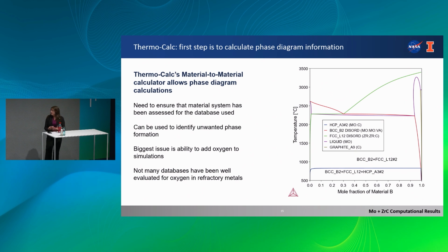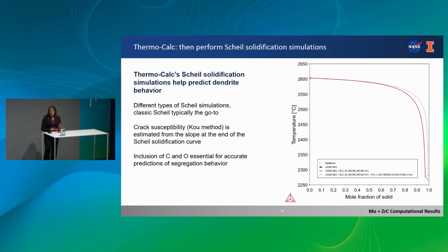So we did a little bit of phase diagram modeling first to determine whether or not we might get some unwanted phases forming. And the biggest issue, though, with this is that a lot of databases, for refractory metals, do not actually include oxygen. And oxygen and carbon can really have a big impact on your properties and the phases you see formed. So this makes a lot of this modeling a little bit more difficult. We also did some Scheil solidification simulations, and as you can see, this can help. We can use the Scheil solidification simulation to help predict the dendrite formation and behavior. But once again, the biggest issue with this is that if you don't have any oxygen, you actually may get different dendritic phases being formed. That said, this can give us at least an estimate on crack susceptibility.